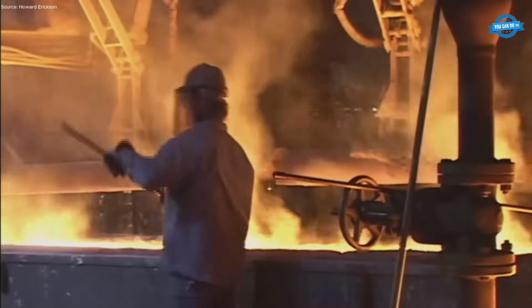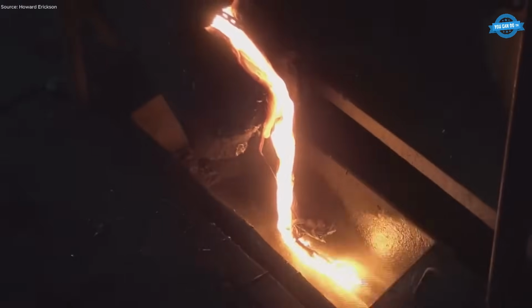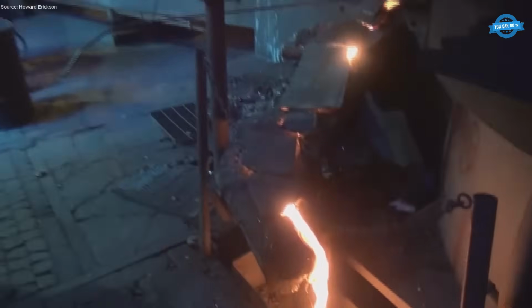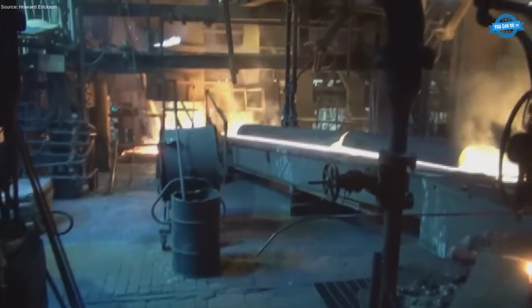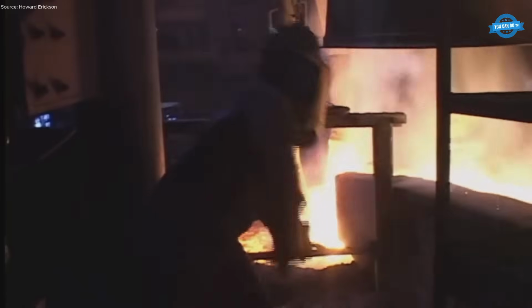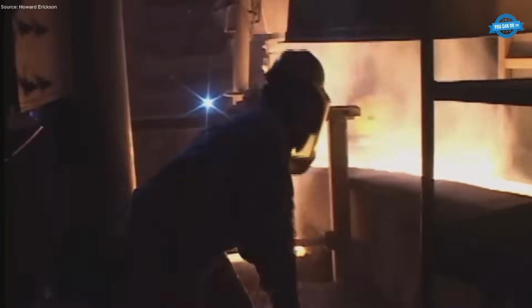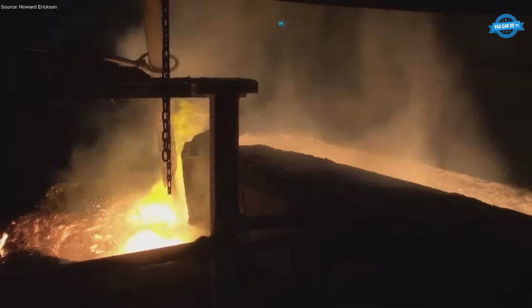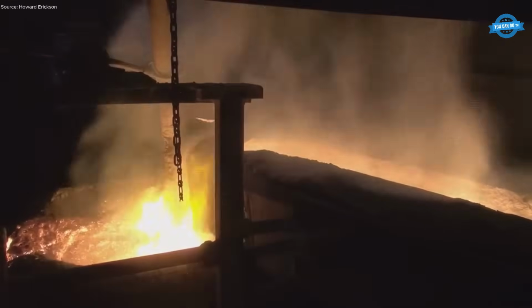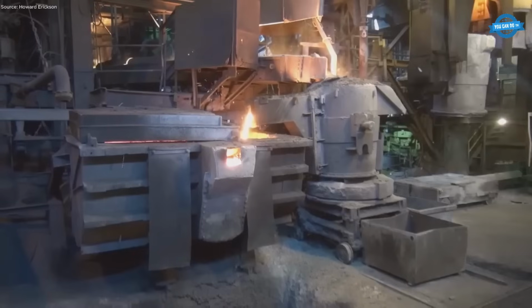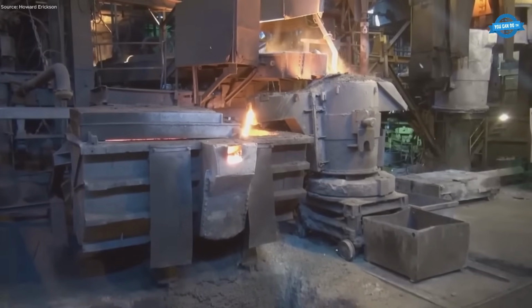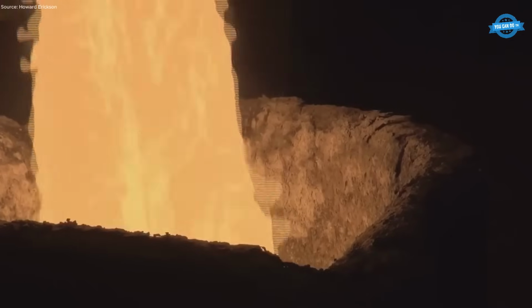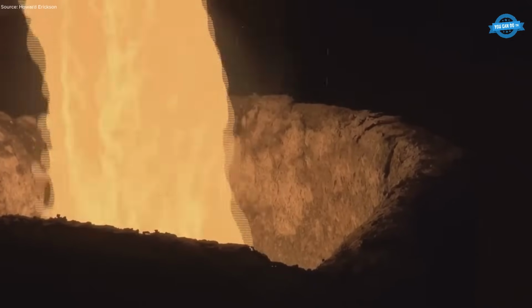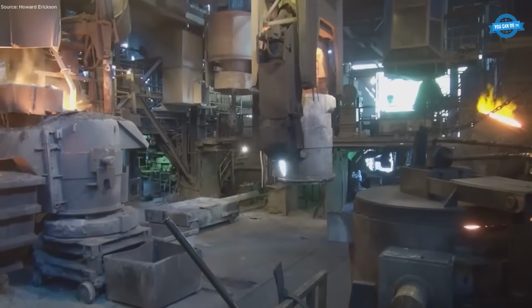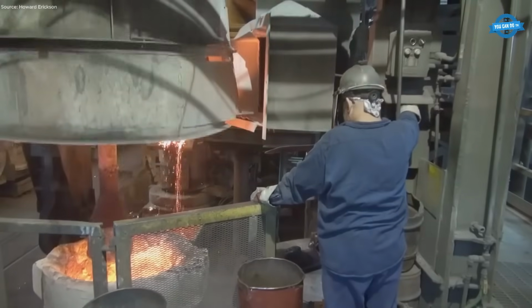Once the base iron reaches the required composition, it is transferred into treatment ladles for the critical spheroidization stage. In this step, magnesium ferrosilicon alloy is placed in the bottom of the ladle, and as the molten iron is poured in, an exothermic reaction occurs, transforming flake graphite into spheroidal graphite. This structural change is what imparts ductility and toughness to the final product. The reaction is tightly controlled with respect to temperature, alloy quantity, and time, and all parameters are recorded for quality assurance. Immediately following treatment, the molten metal is poured into centrifugal casting machines.